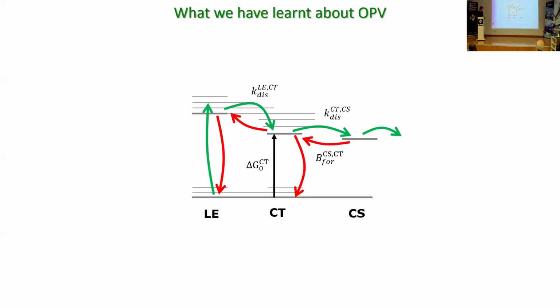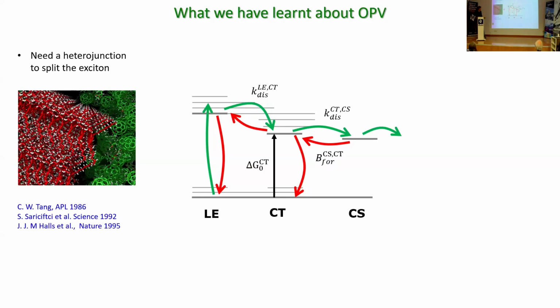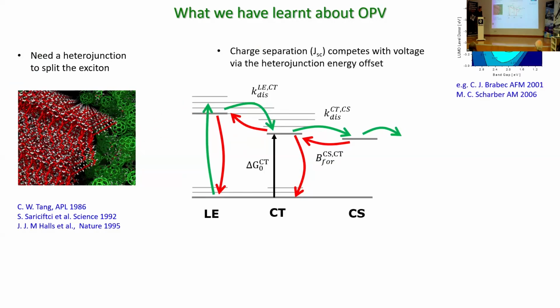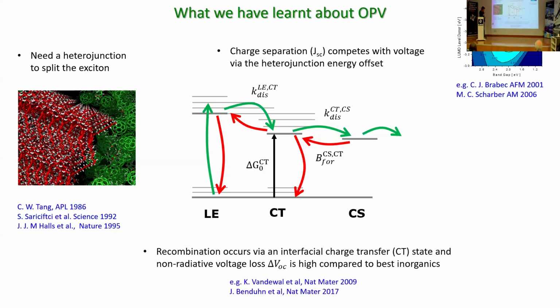So if we think about the things that are accepted about these materials, it's convenient to think about it in terms of a competition between the separation of this exciton into charges and the recombination events that compete with that. What do we know? What is pretty much accepted is that we do need some kind of heterojunction to split the charges. Once you have a heterojunction, you can generate a photocurrent, but then you have a competition between photocurrent generation, for which you would like to have a large offset, and voltage generation for which you would like to have a small offset. And so there's a compromise there.